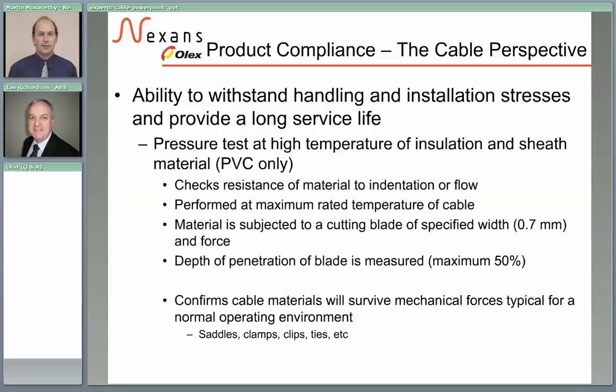One of the other tests is a pressure test. This test is done at maximum operating temperature of the material, and is performed by subjecting the material, PVCs and other thermoplastic materials, to a cutting blade of set width with a specified force, and measuring the depth of indentation or penetration of the blade. Since PVCs are thermoplastics, they are more prone to material flow at high temperatures, and so this test confirms that the cable materials will survive the mechanical forces that are typical for a normal operating environment, like forces from cable saddles, cable clamps, clips and cable ties and so on, because you don't want cable fixing devices penetrating the insulation and causing failure. The pass criterion is a depth of penetration of no more than 50%.